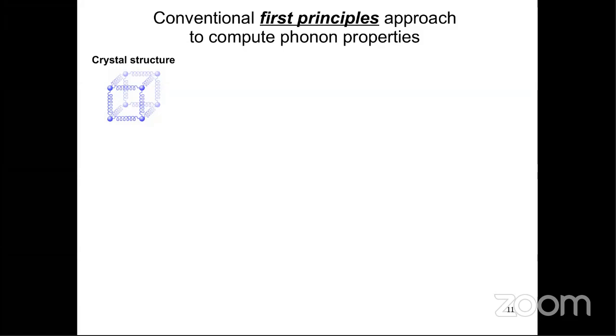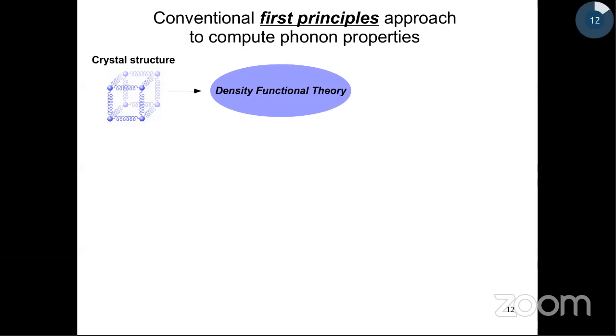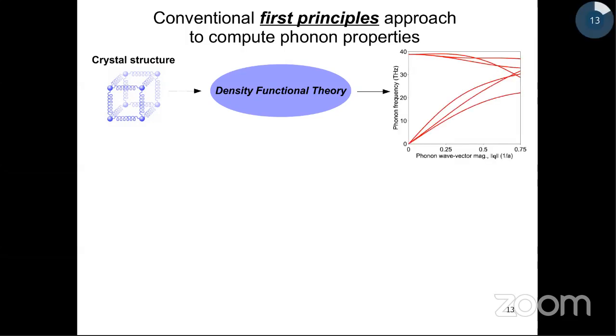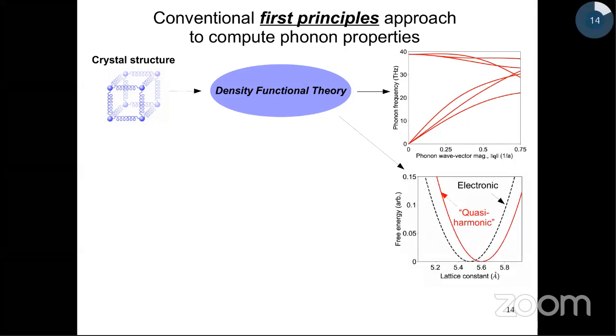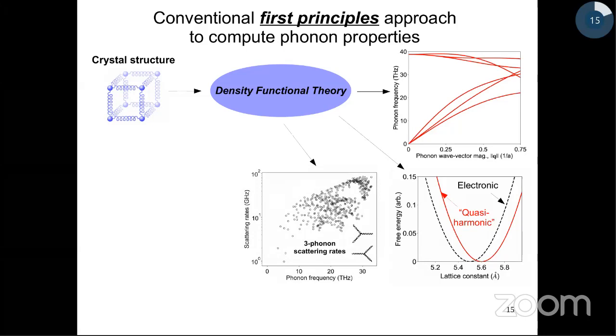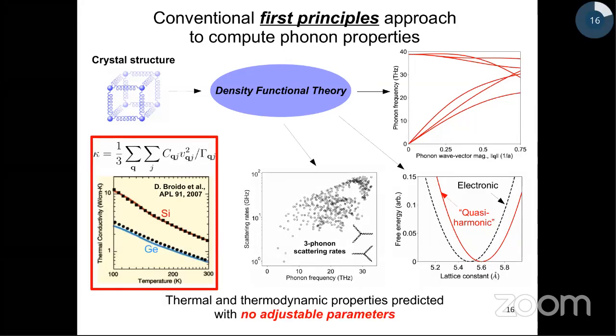So to give you a quick overview of this first principles approach, all that we need to know to get the properties of a material is the crystal geometry, the types of atoms and the number of atoms that go into the crystal structure, and also a representation of the core and valence electrons in the crystal structure. That's it. So with just this information, we can crank it through the density functional theory machinery and calculate properties such as phonon frequencies, dispersion, the free energy, including the vibrational component, phonon scattering rates, and putting these all together, we can also calculate the total thermal conductivity of any material without any adjustable parameters.